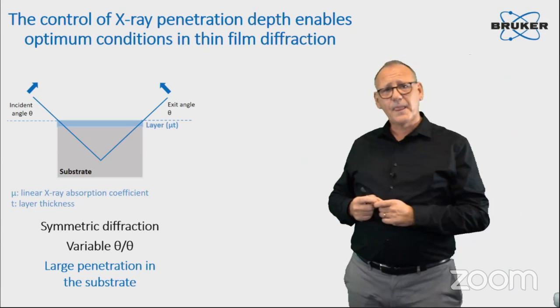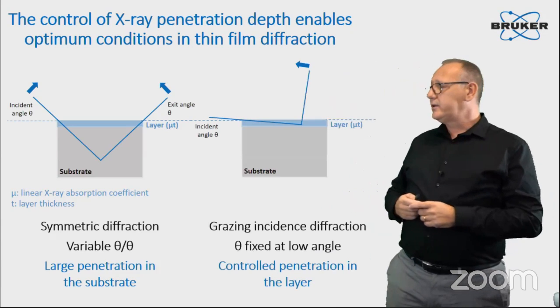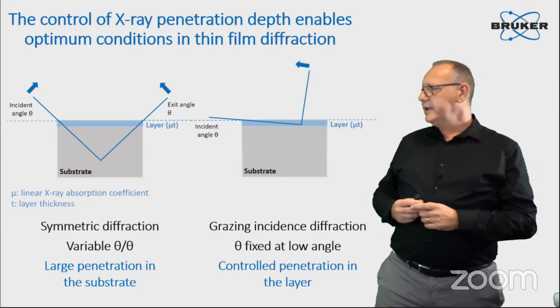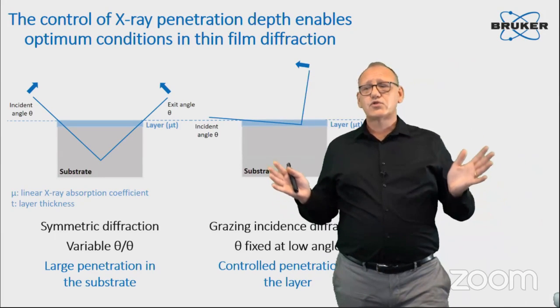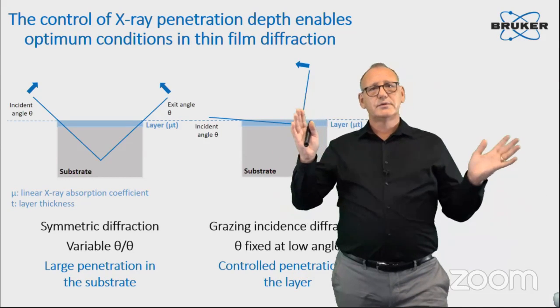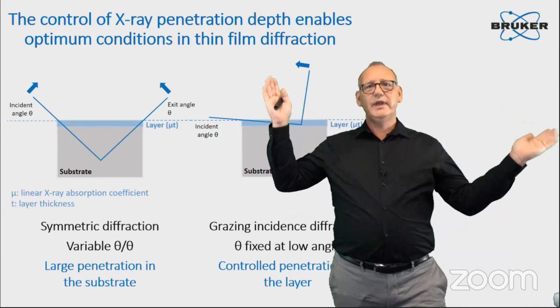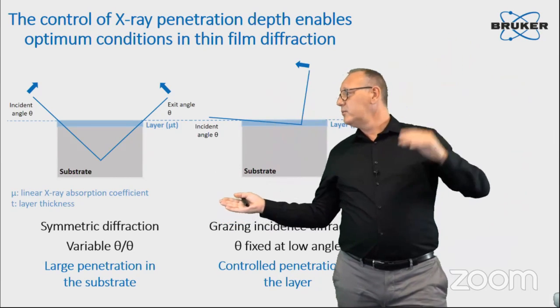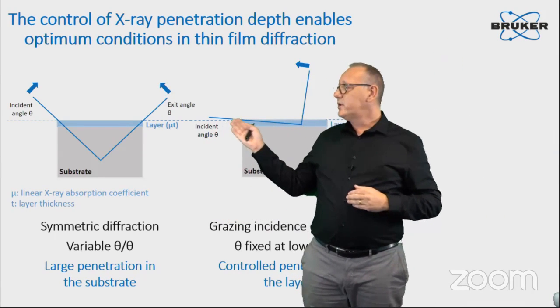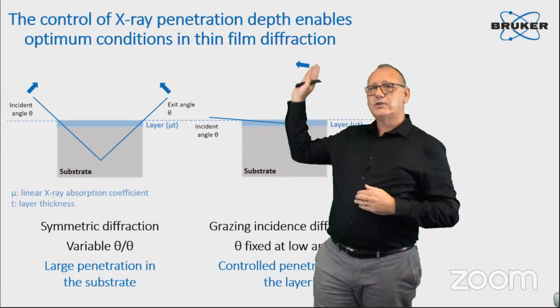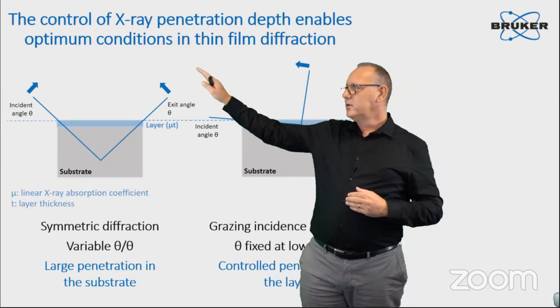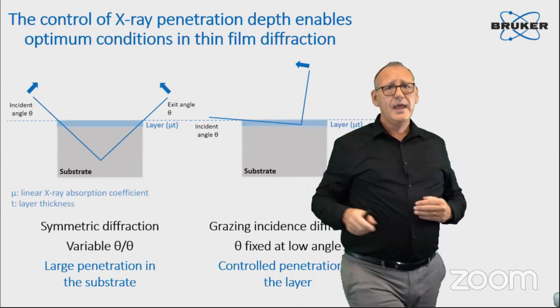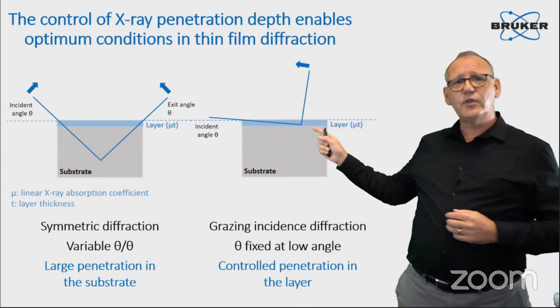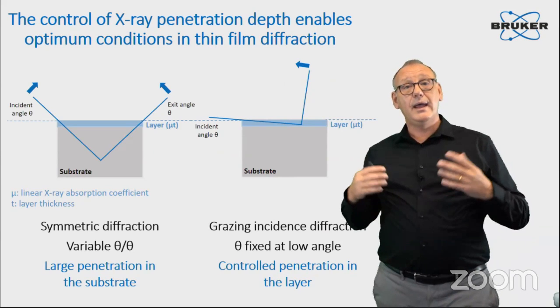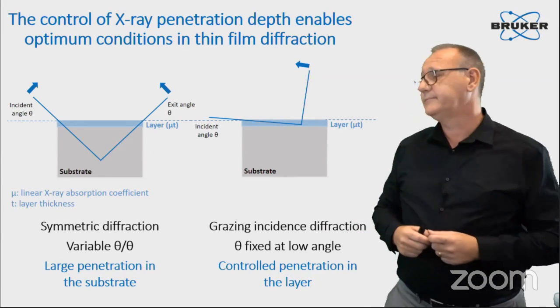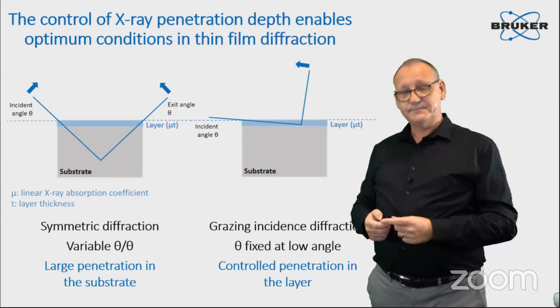A much better strategy to measure this kind of sample is by using the same equipment, but trying to decouple the position of your drives. So instead of staying symmetric, you incline your tube to one side, having a very grazing incident angle, and you keep it fixed during the measurement. And what you do then, you simply scan the detector to screen the Bragg conditions. In that case, you will be able to control the penetration depth into your layer and hopefully emphasize the signal of your layer. So let's see an example.